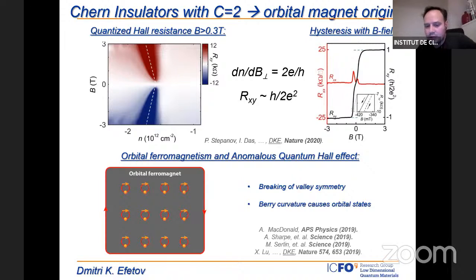And basically, the conjecture is the following: we think that there is really strong symmetry breaking in the system, and that we can think of the flat bands as consisting of degenerate systems of Chern bands with Chern numbers 1 and -1. Depending on the filling of those bands, we can get all the different Chern numbers in the system. So we can get bands with Chern number 3, 2, or 1, or -1, or -2, or -3.